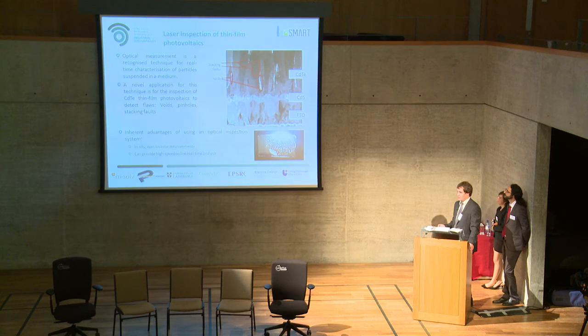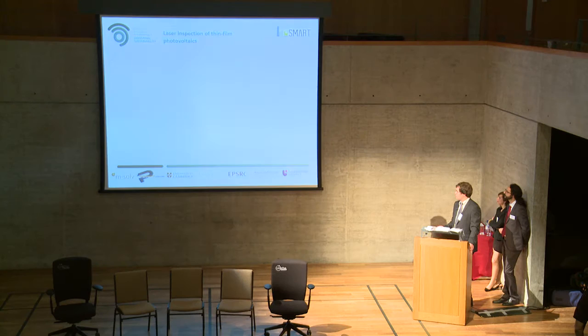So we're shining a laser, a camera is essentially videoing it with some computer software doing rapid image analysis as we go along, and it allows the panel quality to be inspected during production. So we don't have to pull samples off the production line and then spend hours preparing them in order to put them into an electron microscope. We can do it very quickly while the production process is going on. Then we can tweak the settings, production settings, parameters at the time to keep it under control.